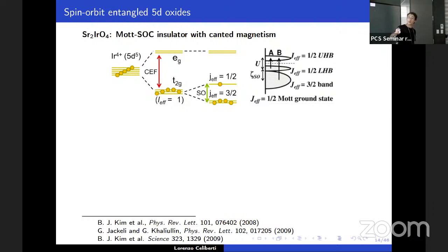If you look at the D orbitals, you have the crystal field, so the splitting of e_g and t_2g. Then you have the further splitting from spin-orbit coupling into the pseudo-spin multiplet J=3/2, which is full here in strontium iridate, and this half-filled J=1/2 doublet. So as you add the Hubbard interaction on top of this, it basically splits into the upper and lower Hubbard bands, as depicted in this picture here. So this is basically how the electronic structure of this material has been explained.